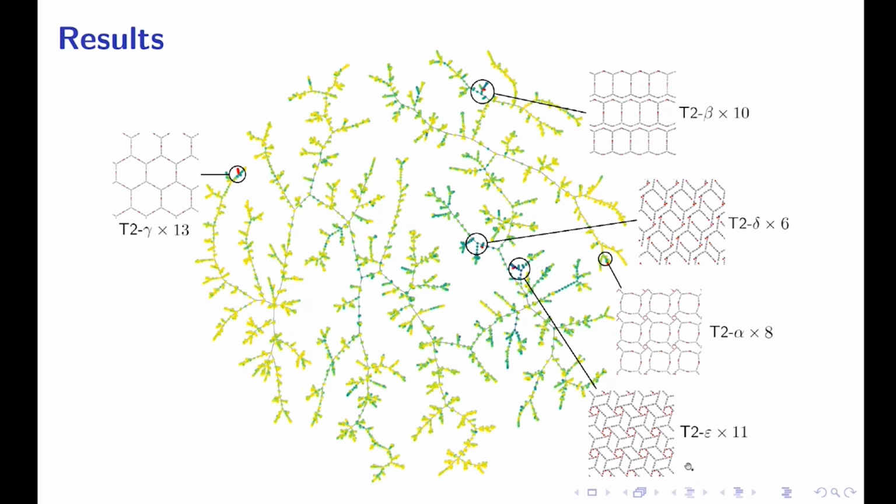And here's a quick picture of the data set I mentioned earlier, the CSP run T2, which found 5 experimental crystals. These are the actually synthesized ones out of the 7,000 or so. And this is a minimum spanning tree containing all the crystals. I think it's colored by energy. So these dark spots are where there are energy dips. And the idea is basically that this tree is constructed using our distances. So things that are similar, according to us, should live in these bubbles. And we find that the same crystals repeated many times for all of them, but we managed to put them all together.